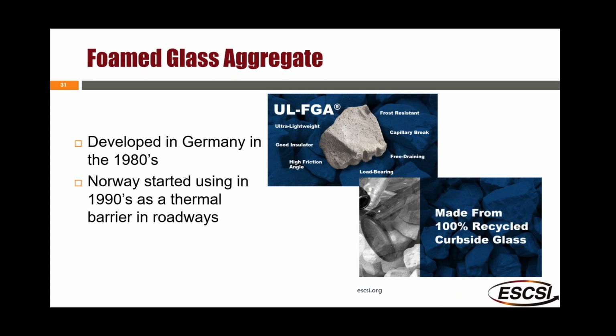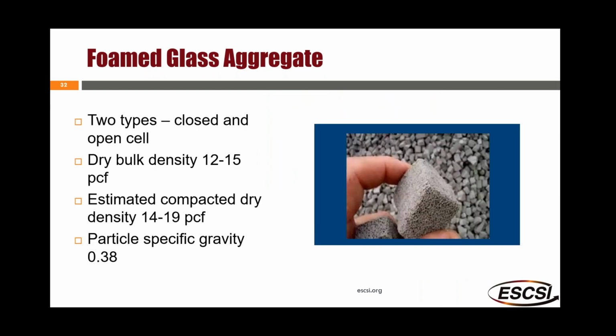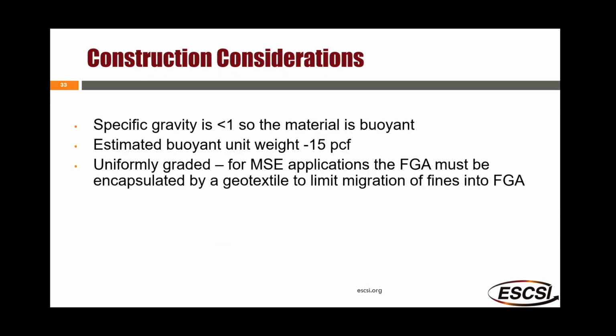As I mentioned earlier, foam glass aggregate is a relatively new player in the lightweight fill market. Although it's not a new player in the national market, it was developed in Germany in the 80s and started being used in Norway in the 90s as a thermal barrier in roadways. It has a dry bulk density of around 12 to 15 PCF, with estimated compacted dry densities in the 14 to 19 PCF range, and particle specific gravities are less than 1, so the material is buoyant, and it's also commonly uniformly graded. So for MSE applications, foam glass probably should be encapsulated or covered with a non-woven geotextile to limit any potential migration of fines.